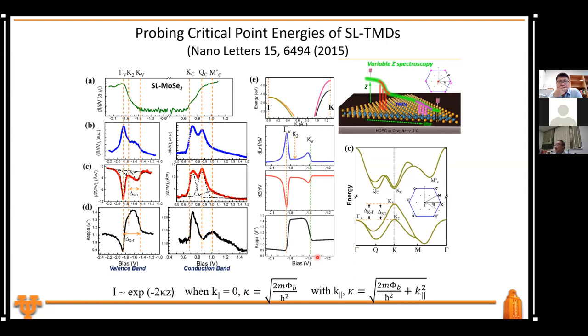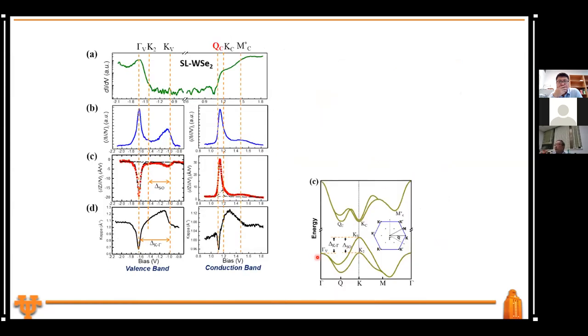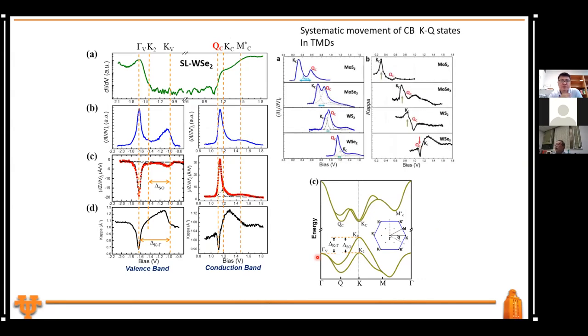Say, well, you can have K resolution in tunneling spectroscopy. Those are due to quasi-particle interference, but here it is due to the K parallel dependence of the tunneling coefficient. So it's more indirect. And by using this, we measured the one for WSe2 and also the one for MoSe2. And then this is what we have observed.